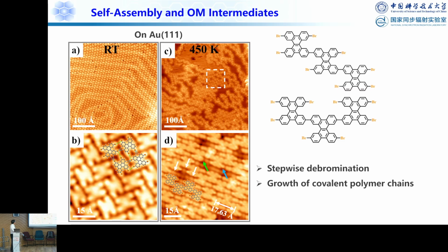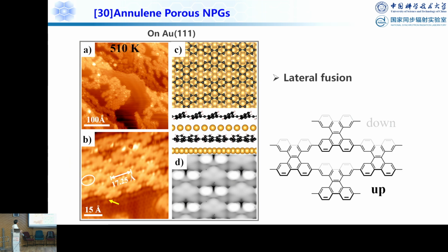Now if we change to gold, it again forms this well-ordered self-assembled structure, the same as on the silver 111 surface. But if you increase the temperature, you can see immediately that you have this C-C bond on the surface, and this is assigned to the gold atom in between here. If you go further to a higher temperature, you see this two-dimensional sheet, and you can see the 14- and 30-annulene pores on the surface. Because they are very close to each other, they show a nonplanar structure, which we observed here.